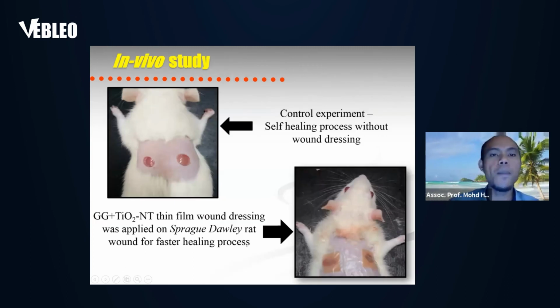Next, we study the performance of our sample GG plus titanium dioxide nanotube for wound healing. This is the original rat. We create wounds in the body of the rat, two wound areas in this rat. The control experiment is the self-healing process without wound dressing. And then for the second sample, our GG plus titanium dioxide nanotube thin film wound dressing was applied on the rat's wound for a faster healing process.